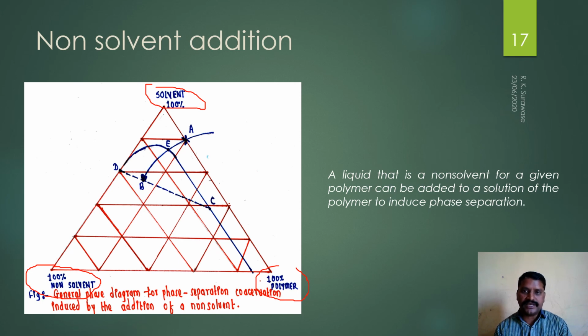The resulting mixture is heated to generally 50 to 55 degrees Celsius, and at this temperature, isopropyl ether, a non-solvent, was added slowly. This affects the phase separation, coacervation.